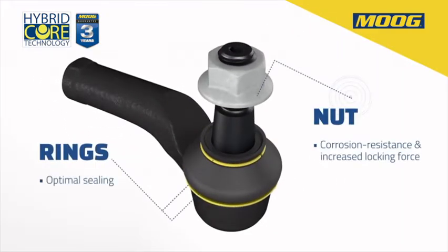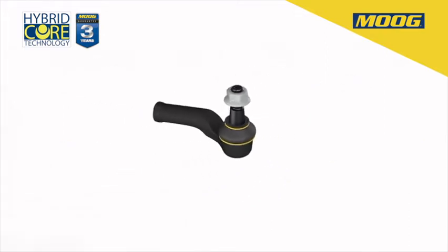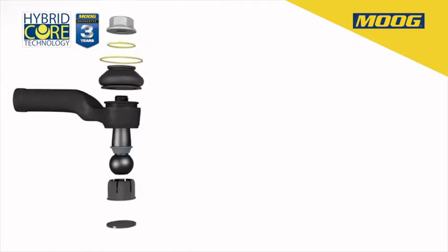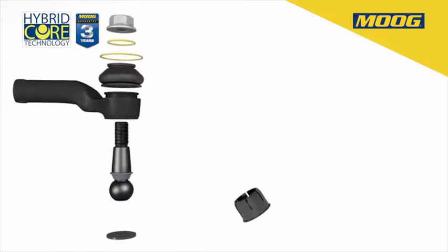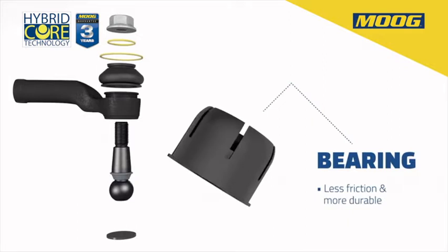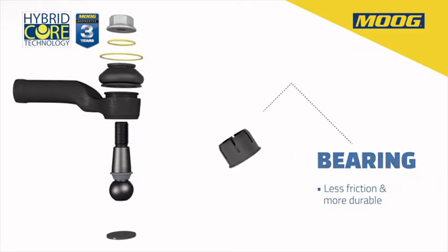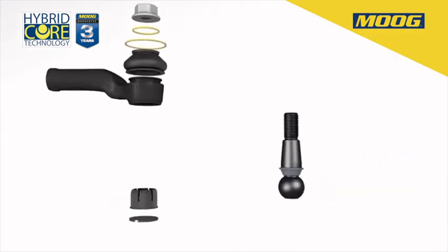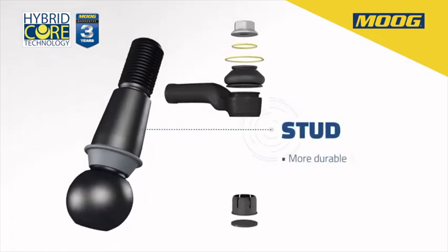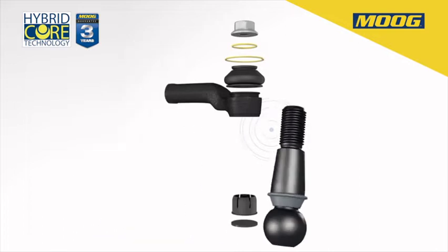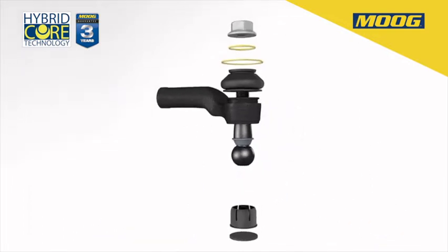These elements are subject to high stresses, so we need to be sure that they function optimally throughout their life. That's why Moog manufactures them with hybrid core technology, the new synthetic grease, metal sealing rings and flanged and zinc flake coated nuts. These combined technologies ensure the highest level of efficiency of the parts in operation and a long service life in optimal conditions once installed.